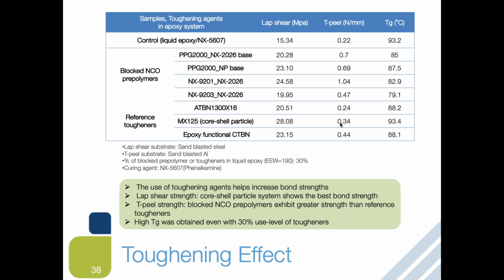Now for T-peel strengths, at least in this study, blocked pre-polymer has shown better performance than the toughener. And when it comes to TG comparison, of course, the core shell particle has shown the best TG performance in this regard. However, even blocked pre-polymer, in some cases, has shown high TG.